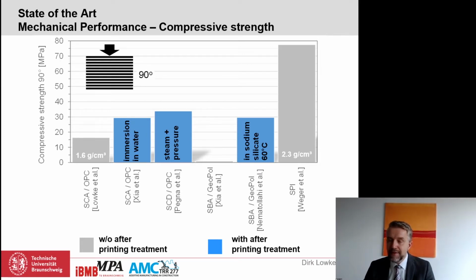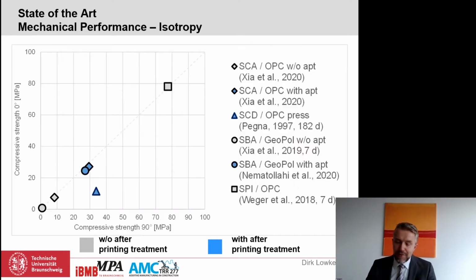In contrast, the selective paste intrusion here on the right side achieves normal densities of about 2.3 gram per cubic centimeter and correspondingly significantly higher strengths of up to 78 megapascal so far. And finally, I want to address the isotropy of these materials. In this graph, the strength is shown perpendicular and parallel to the layer structure. And as you can see, the current experience shows that no directional dependence of the material properties can be observed for the particle bed binding process.